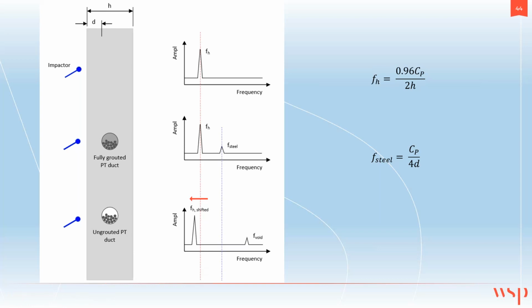This lower frequency is called shifted frequency and is an important indicative of potentially having voids in a PT duct. The other thing that we notice is that for ungrouted duct, we are going to miss the peak for steel, which should have been where the blue line is. But then we'll get a higher frequency for the void, which is calculated using this equation.